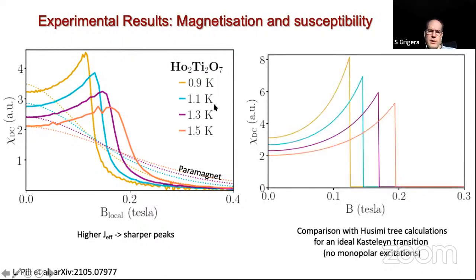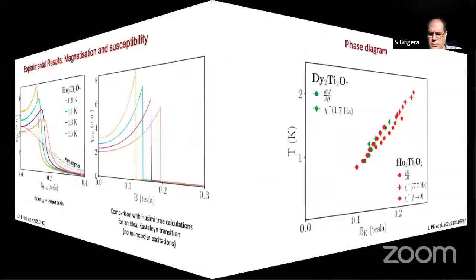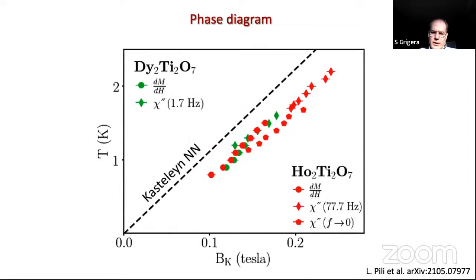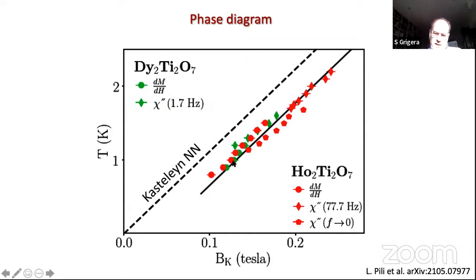And the reason why we did both holmium and dysprosium is because they have the same moment, but they have completely different J. So in the case of dysprosium, J is 1 K, and for holmium it is twice that value. Okay, so again, you see here, because J now is a little bit higher, these are also stronger. The comparison with this is the symmetry calculation of what you would expect for that type of topological transition. You see that the experiments look pretty similar to what you would find. So I come to the phase diagram. This is how they look, and you see I put together here what you get from different techniques, like measuring different samples and also measuring AC susceptibility and DC susceptibility and SQUIDs. And you see that in both cases you get a single line with error.